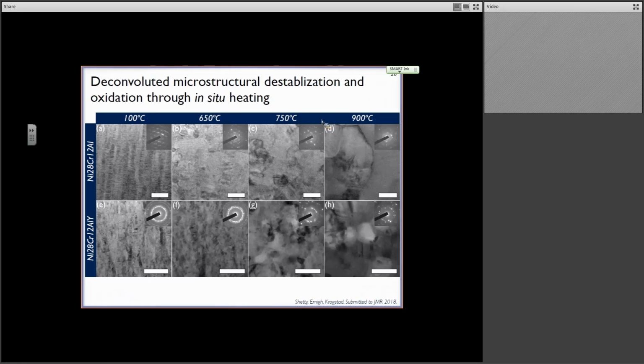force for oxidation. And so what I'm showing you here is on the top row is a nickel chrome aluminum alloy, and on the bottom is a nickel chrome aluminum yttrium alloy, right? Otherwise, the chemistry is the same as the bottom row has yttrium, and then we have these different time steps. So we see that we start, and these are at 100 C already, but the as deposited structures are quite similar. Columnar microstructure. We're not going to talk about these planar faults just yet, but all these striations, that's also a different interesting feature. But they're about the same grain size to start with. By the time we get to 650 C, there's no evidence of this columnar microstructure.